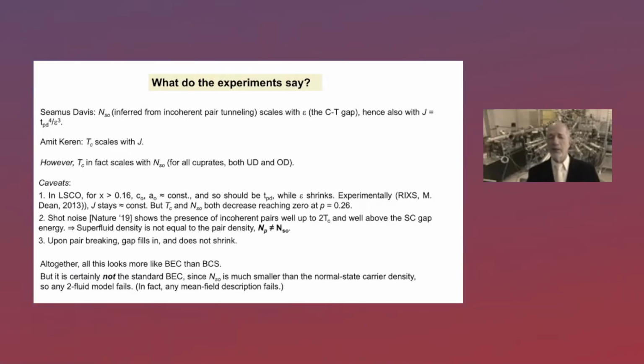Amit Keren, in his talk, presented evidence that in his material, the name of which I cannot even pronounce, Tc actually scales with J. And there was a little bit of debate. Seamus was saying Tc is not a good proxy for superfluid carrier density. I don't know what he meant by that, but what we know experimentally is that Tc in fact scales with superfluid carrier density. To the extent that if you tell me the superfluid carrier density in your sample, I will tell you what Tc is, and you don't even have to tell me whether it's lanthanum strontium cuprate or YBCO, whether it's underdoped or overdoped.